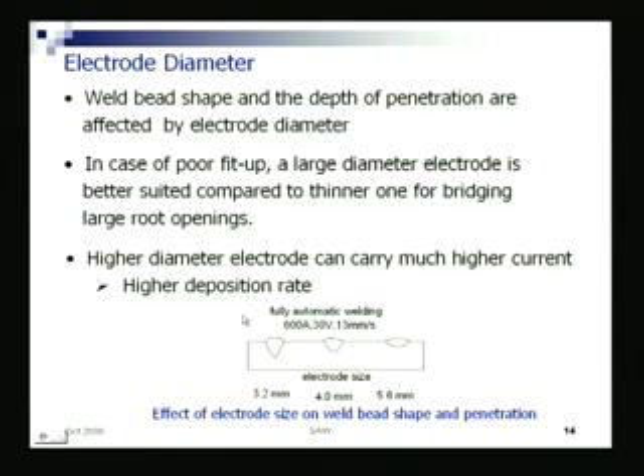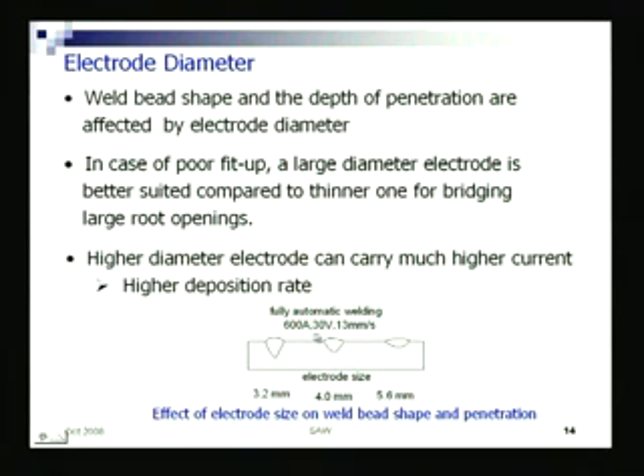Now, if I do not do that, and keep all parameters the same while just changing the electrode diameter, the effect is this. The whole idea of showing this diagram is that with a lesser diameter, you have a higher current density. For the same current condition, say here for 600 ampere current, 30 volts and 13 millimeter per second speed.